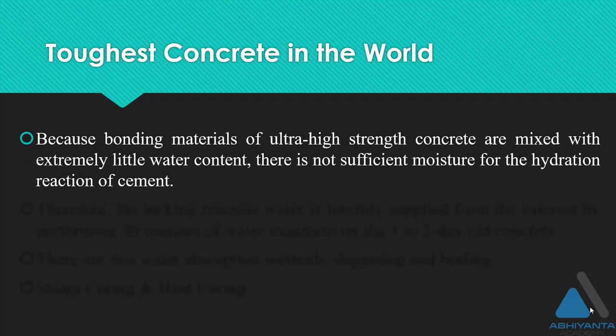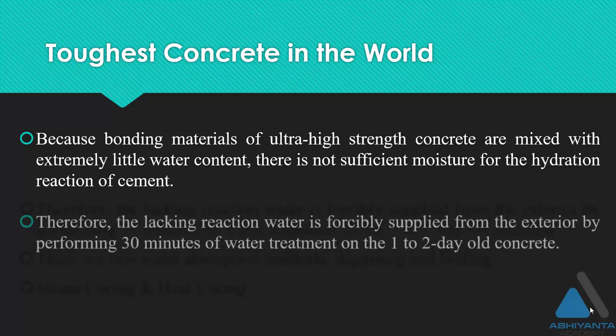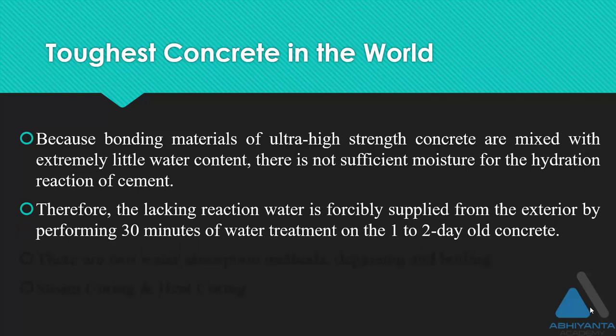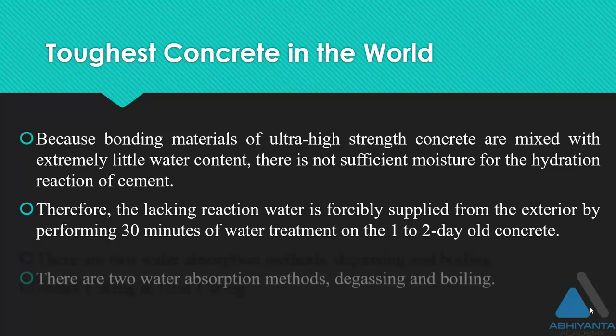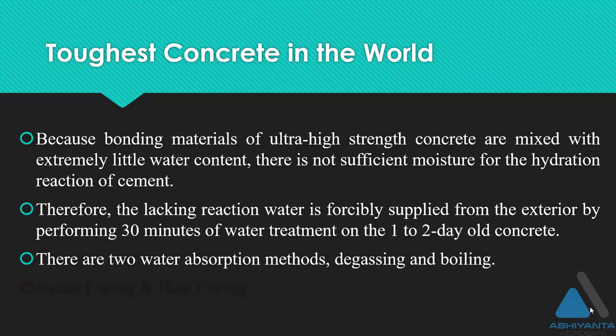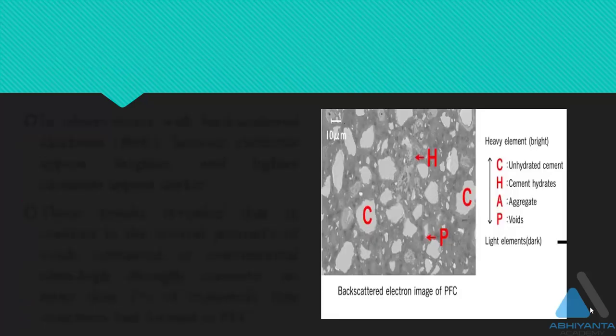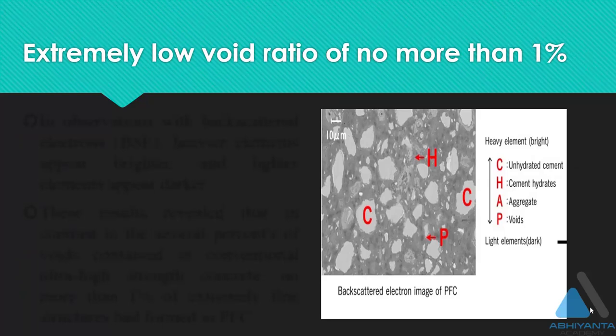Because bonding materials of ultra high strength concrete are mixed with extremely little water content, there is not sufficient moisture for the hydration reaction of cement as well. Therefore, the lacking reaction water is forcibly supplied from the exterior by performing 30 minutes of water treatment on 1 to 2 day old concrete. So here we are applying a curing technique by externally supplying water, because there is very little water content inside the concrete. There are two water absorption methods, degassing and boiling. We are applying steam curing and heat curing during the making of this concrete. We have achieved an extremely low void ratio of no more than 1% in PFC.